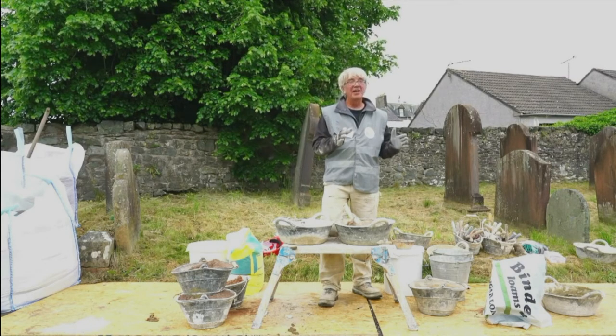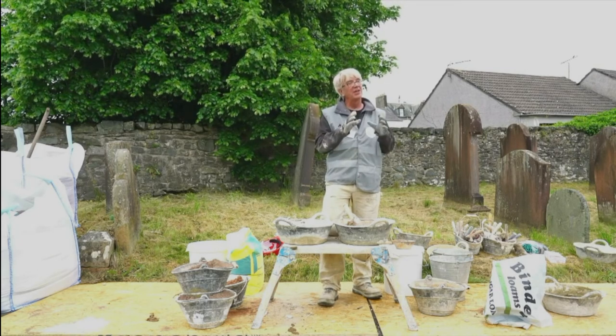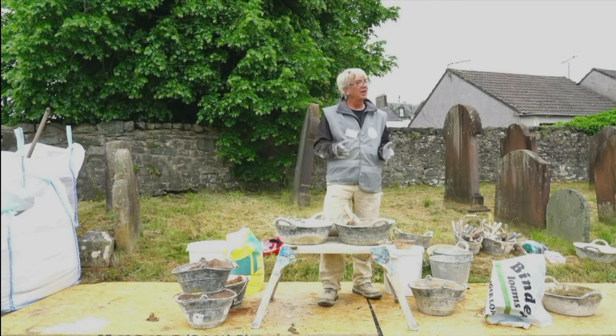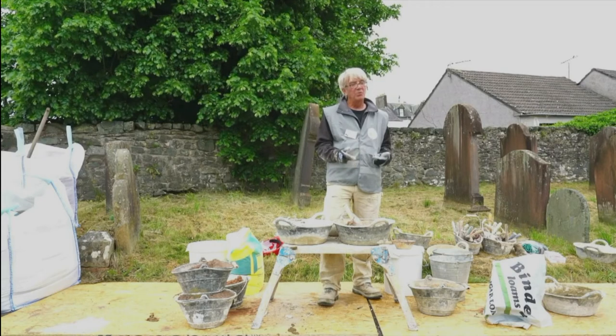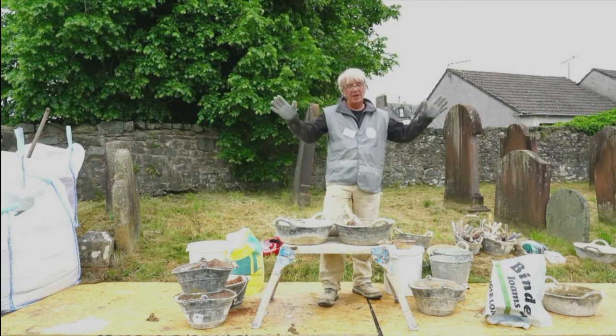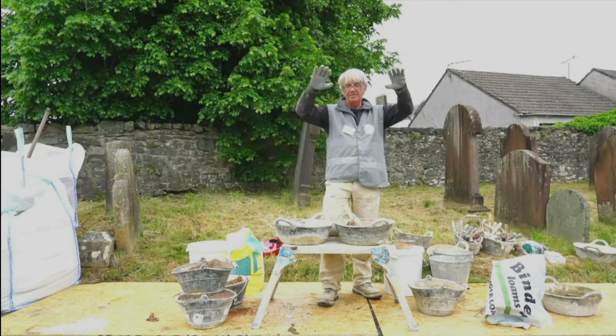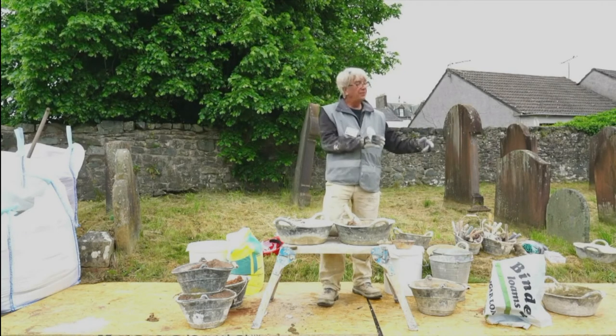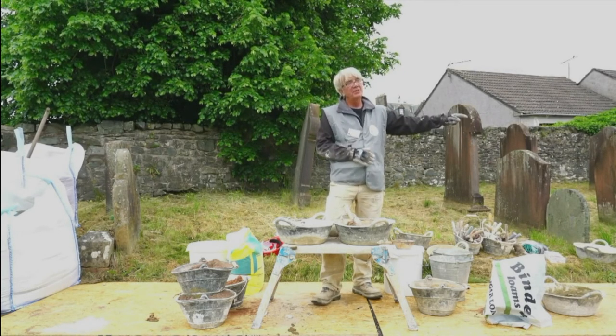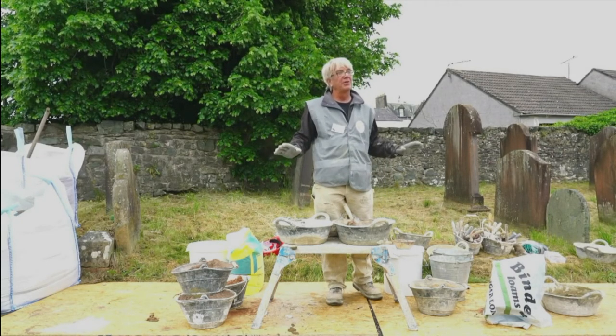The late slaking is a major problem if you use hydraulic lime from quicklime. And again, that's infected our understanding. So you'll get people saying, oh, late slaking, and all this. It's very rare. One of the things at your uni with the practical, we did 8 square metres of plastering on lath, on panels. I did half of it with powdered quicklime that I'd mixed the night before into a plaster, and there's no chance of late slaking, it's powder, for goodness sake.